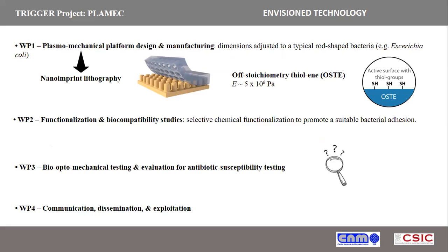So the project includes work package one, which involves the design and manufacturing of the plasmomechanical platform. It will be done by nanoimprint lithography. First, a silicon master will be fabricated by electron beam lithography, coated with a thin gold layer, and then replicated in a polymer called off-stoichiometry thiol-ene, OSTE, which is very interesting for this application for many reasons.